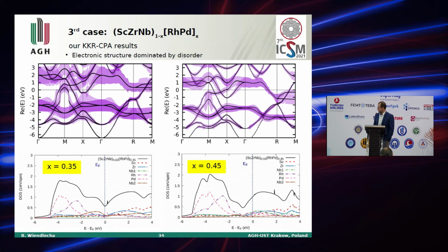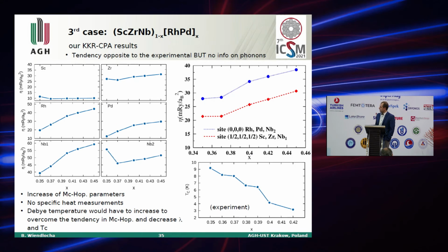So when it comes to the evolution with X, if we increase the concentration of rhodium and palladium, the density of states increases, and also McMillan-Hopfield parameters are increasing. So what we found is opposite to what we expected here, because from the experiment, as I mentioned, TC was found to decrease with X, and from our electronic structure, McMillan-Hopfield parameters increase. However, for this material, we don't have any information on phonons, unfortunately, since the heat capacity hasn't been measured yet.